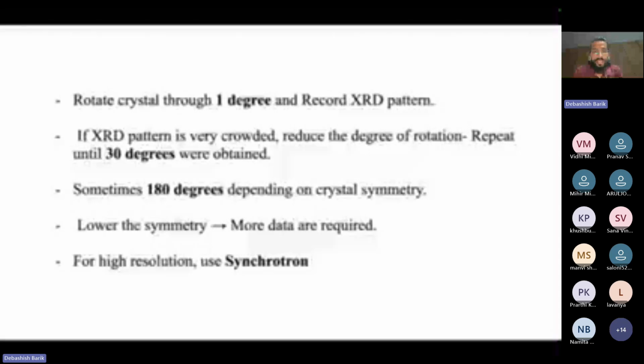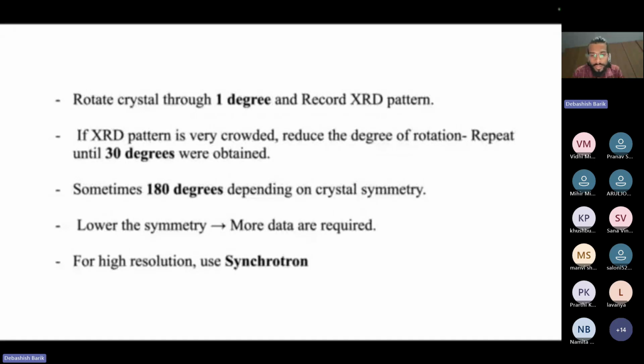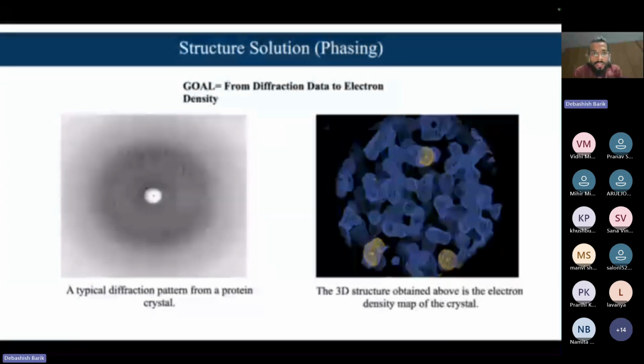So if the XRD pattern is very crowded, we used to reduce the degree of rotation and repeat until 30 degrees were obtained, sometimes 180 degrees depending on crystal symmetry. So the lower the symmetry, the more data are required. For high resolution, we use synchrotron as I already discussed. So after diffracting those crystals, we used to get the diffraction pattern, and this diffraction pattern was recorded in an electronic device.